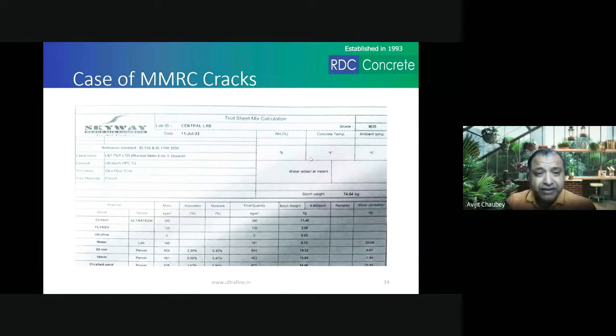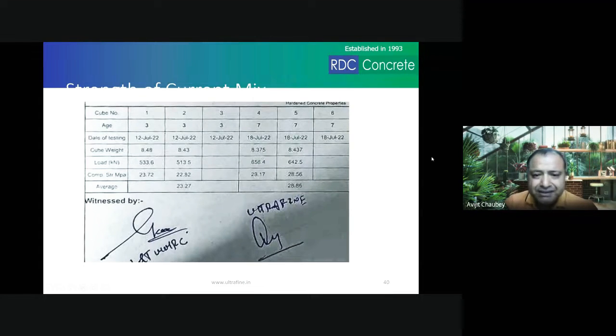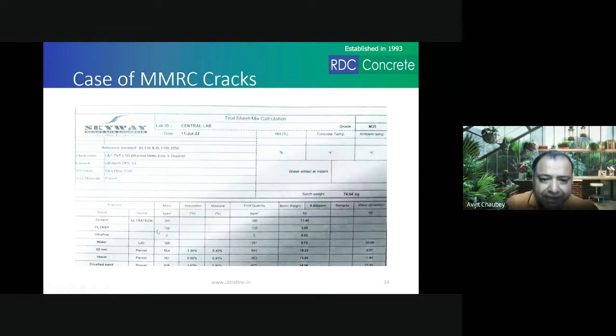This is from Skyway Central Lab for their concrete that they supply for Metro, Mumbai Metro. And if you see, this is without ultrafine. They get a strength of 23 MPa in 3 days and 28 MPa or 29 MPa in 7 days without ultrafine. And the cement content is 380 kgs.